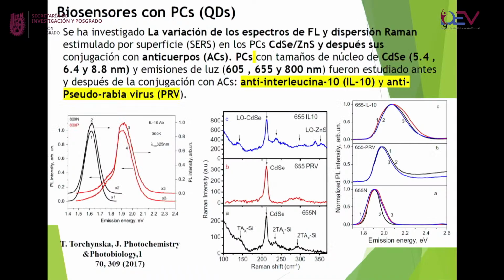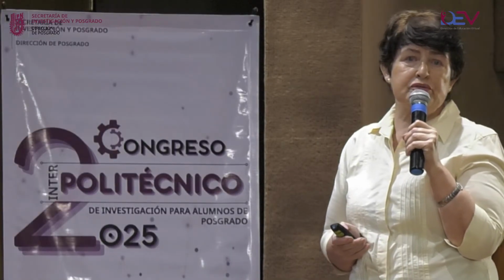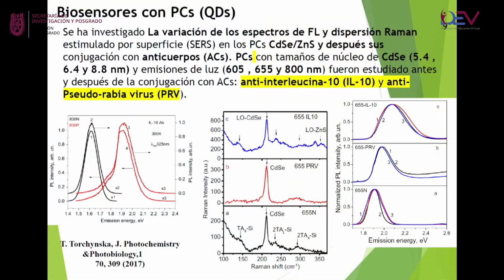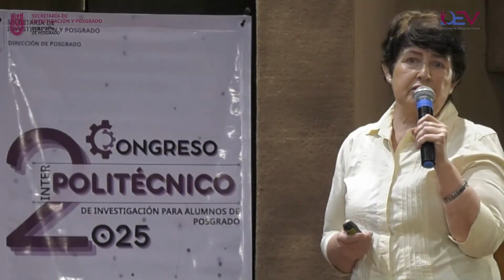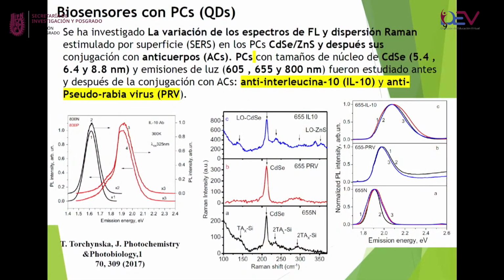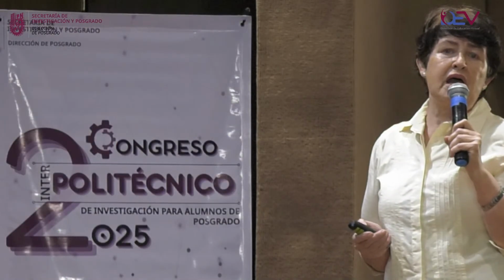I will talk for a short time mainly about our results. When quantum dots started to be used for bioconjugation, it was practically not clear how bioconjugation influenced the luminescence of quantum dots. Because for a biosensor, it's necessary to test the influence of the antibody on the value of photoluminescence. As a result, we investigated the interaction of antibody with quantum dots and the influence of the antibody on photoluminescence spectra and also Raman spectra of quantum dots.